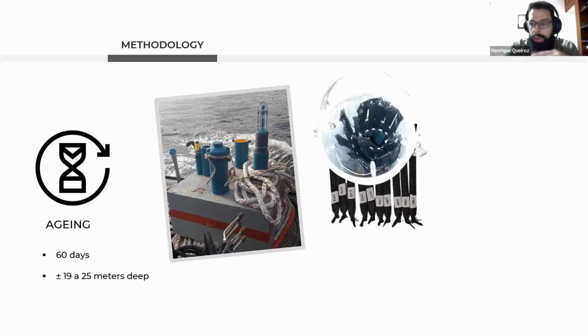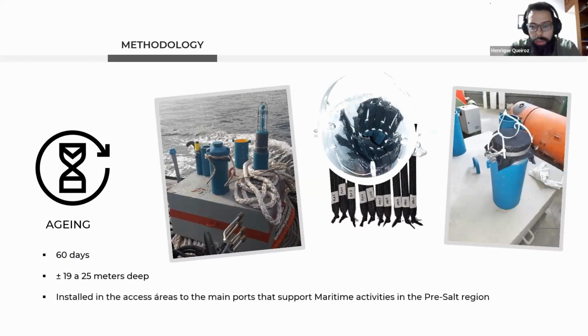So we have our tensile and our flexural specimens, and we put them into these little nylon bags with perforations and inside of that vat structure. And so it allowed the ocean water to go through completely, right? And it was 60 days. And the depth changed, varied by approximately 19 to 25 meters. It goes up and down a little bit.